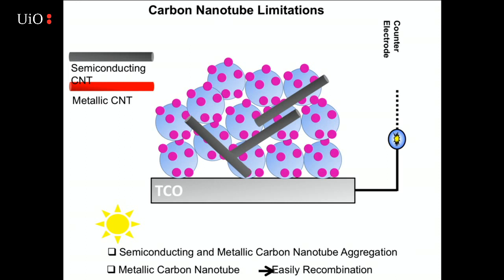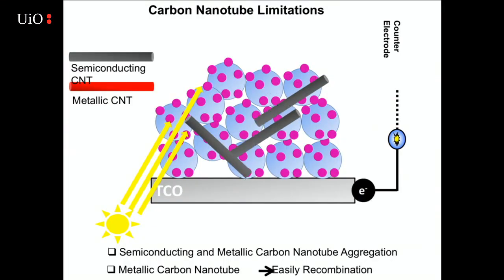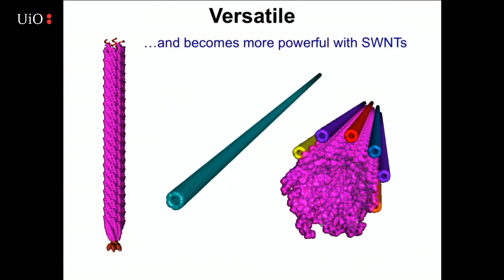So the idea was to add carbon nanotubes to these kinds of structures, and people had worked on this for years and found that the carbon nanotubes had actually decreased the efficiency, not increased the efficiency. So what we worked on was using semiconducting carbon nanotubes and using a virus to help assemble these materials in the right kinds of locations. And so the idea was that you would have the electron that would find the virus-based carbon nanotube complex and then be able to find an easier path.